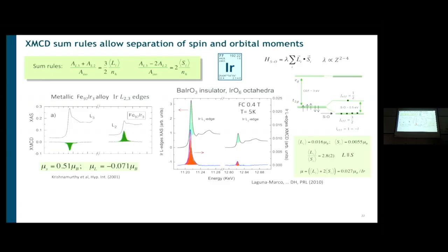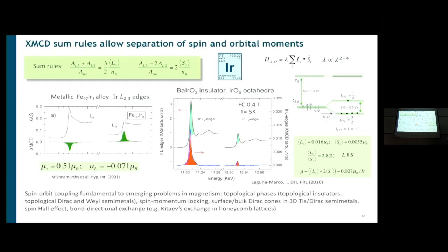And you can actually quantify it, and in this case, the orbital angular momentum is almost 3 times larger than the spin angular momentum for this particular iridium 5D 5 configuration in the presence of spin-orbit coupling. So this is a very important feature of XMCD because, as you know, spin-orbit coupling is at the very root of many, many modern effects in topological materials. So you have spin momentum lock-in, you have band gap openings in the Dirac cones, you have spin transfer torque, Kitaev exchange anisotropy, all of that has to do with spin-orbit coupling. So the ability to separate the orbital magnetization from the spin magnetization is quite a plus.